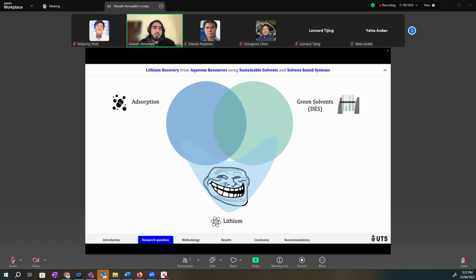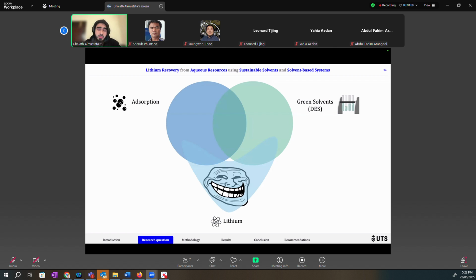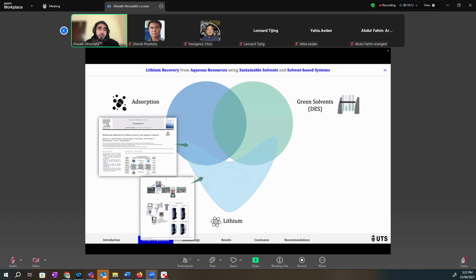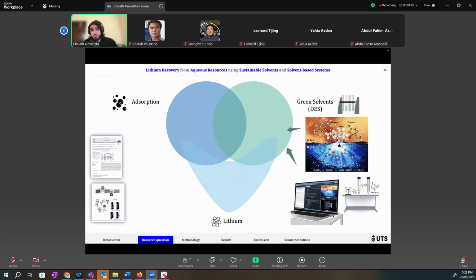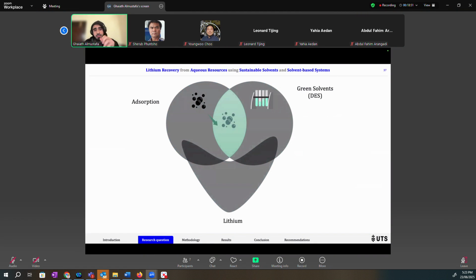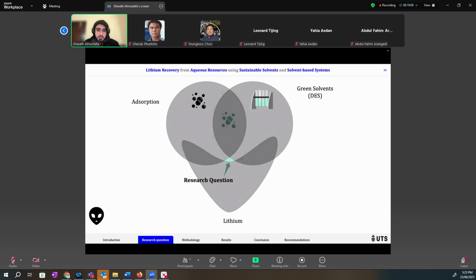But I found that some of the studies do integrate deep eutectic solvents with adsorption. However, none of them are applying them for lithium, or very, very minimal research has been done on that field. We have tons of studies doing adsorption of lithium from different resources, and we have a lot of studies on the field of green solvents or DESs. Even our group previously has done such studies. But the intersection of deep eutectic solvents used within adsorption of lithium was something that needs to be investigated. Ideally, I wanted to look at the intersection of all three, but this research question is still pending. And in order to answer it, we needed to investigate the surrounding areas of that question.